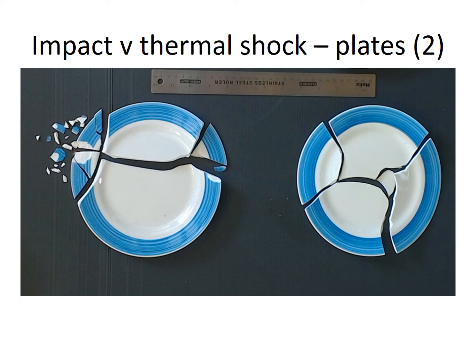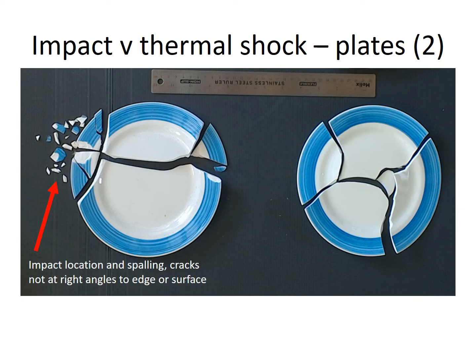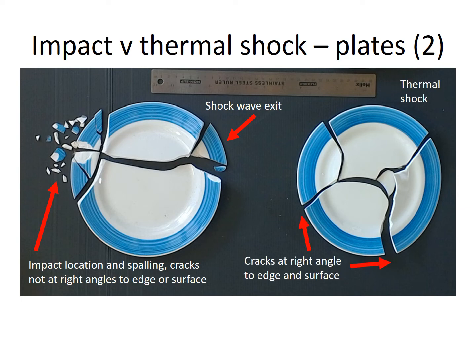Here is a second pair of plates of a slightly harder, semi-porcelain type fabric. The left-hand plate was dropped on its edge. This has produced a large amount of spalling at the impact point, and where the shockwave exits the plate, a single large sherd has come off. The right-hand plate was subject to extreme heat. Again, the impact and thermal fractures look very different.